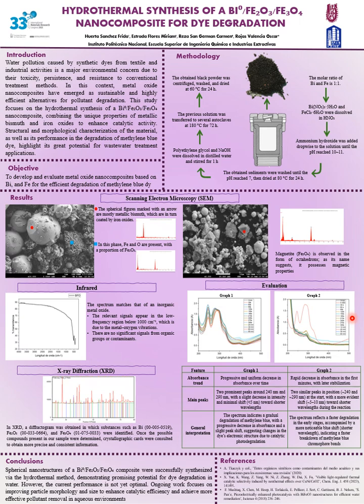General interpretation. The spectrum indicates a gradual degradation of methylene blue, with a progressive decrease in absorbance and a slight peak shift, suggesting changes in the dye's electronic structure due to catalytic photodegradation. The spectrum reflects a faster degradation in the early stages, accompanied by a more noticeable blue shift, shorter wavelength, indicating a faster breakdown of methylene blue chromophore bonds.